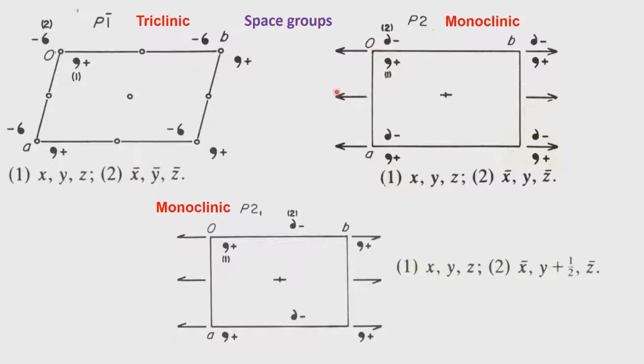This half-distance repetition allows this point to be related by a two-fold symmetry. So, it not only generates that point by the normal two-fold operation, the translation by 1 unit is generated here, and these 2 objects are related by the two-fold symmetry. These are the 2 objects we will see in this space group, and therefore Z is equal to 2.